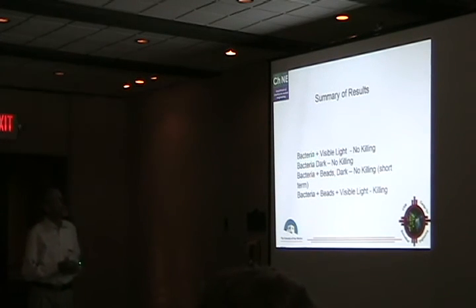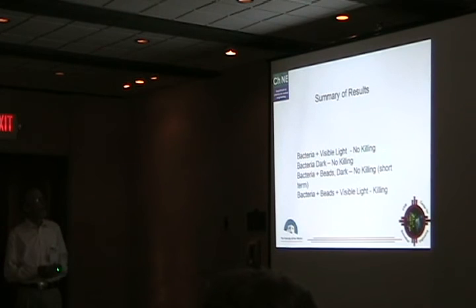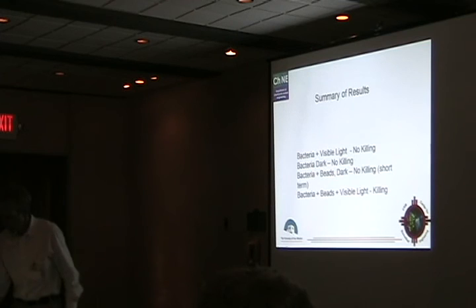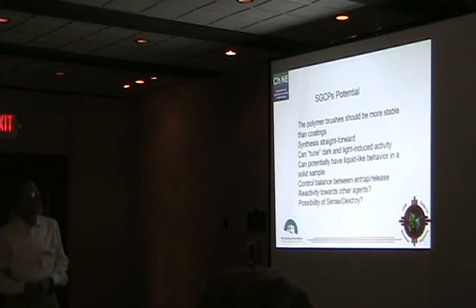To just summarize here: bacteria plus visible light, no killing. Bacteria in the dark, no killing. Bacteria on the beads in the dark, no killing, at least in the short term. But with visible light, bacteria and beads, the bacteria are killed. They may even be degraded, from what we've seen with some flat surfaces of this. So we think these grafted polymers can be very useful.